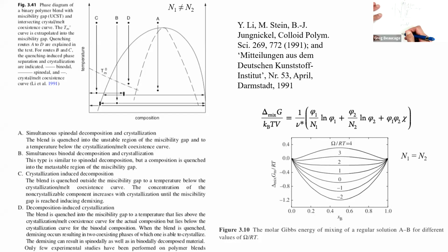So for spinodal, you don't get that. For spinodal, you start with these fluctuations, and dC/dr is negative. You have to grow the fluctuations uphill. Like if this is composition, this is position, you're moving material uphill, and it's going to grow like that. So you have like reverse anti-diffusion going on. It's going against the concentration gradient. So all it is doing is enhancing these natural fluctuations that happen, growing the phases.